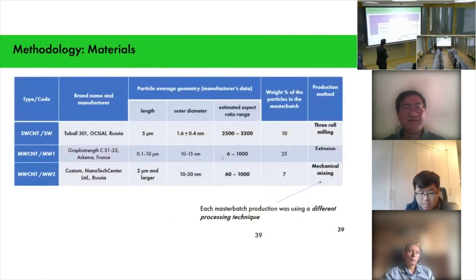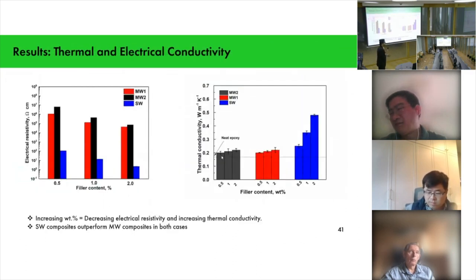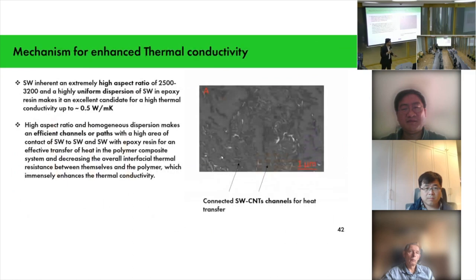You see, for the single wall, it is three roll milling for extrusion and it's mechanical mixing. So I feel that for the mechanical mixing that industry uses, they didn't mix it properly, because at such a low weight percentage, you need very, very homogeneous mixing.